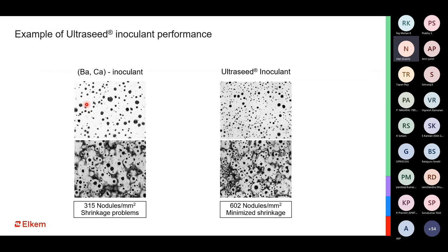I'll just give you, this is just one of the examples that when we have the same kind of casting, when we have the same kind of solidification rate, if you use a barium calcium inoculant, you would get a comparatively lesser nodule count. I'm not saying that the barium calcium inoculant is not a good inoculant, but then it has its own limitations. So in this particular case study, we had seen that when we were using a barium calcium based inoculant, we are getting a much poorer nodule count, and thereby also we are having a higher shrinkage tendency. On the other hand, when we use the ultra seed based inoculant to produce the same kind of casting at a same addition rate, we got a much higher nodule count, and we were able to thereby also control the shrinkage tendency in the casting. So this is just to reinstate the role of inoculation, both on the improvement of nodule count as well as the control of shrinkage.